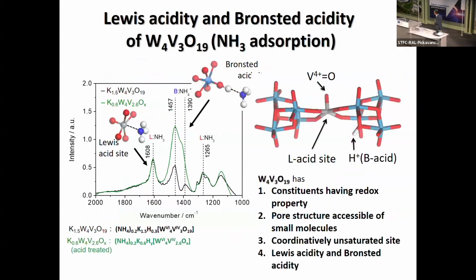For the acidic property, we conducted ammonia adsorption and FTIR analysis of this sample. Then you can see Lewis acidity as well as Brønsted acidities in this material. So we can assume that the Lewis acidity comes from the square pyramidal vanadium species where you have a vacancy in this. So therefore it can play a role as a Lewis site.